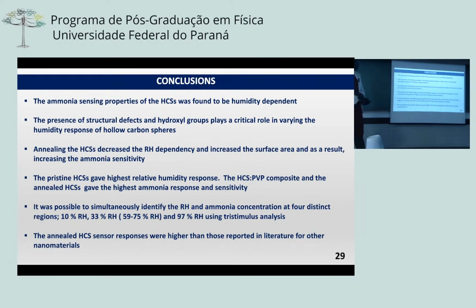Anyway, so in conclusion, I can say that the ammonia sensing properties of the hollow carbons were found to be humidity dependent, and the presence of structural defects and hydroxyl groups plays a critical role in varying the humidity response. The most important thing is that by annealing, you're able to decrease the relative humidity dependence, with the pristine giving you a higher relative humidity response and the annealed giving you a higher ammonia sensitivity.